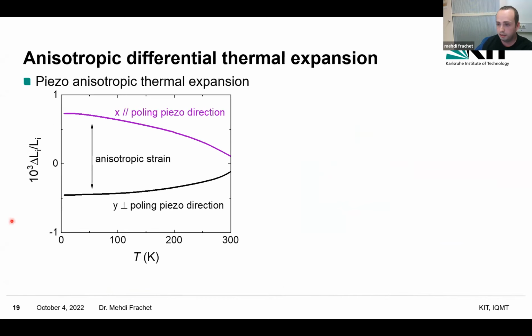So you can see the thermal expansion of the device as a function of temperature, both along the poling direction and perpendicular to it. This was done by Christoph Meingast and Anna Böhmer. And you see that there is a difference.